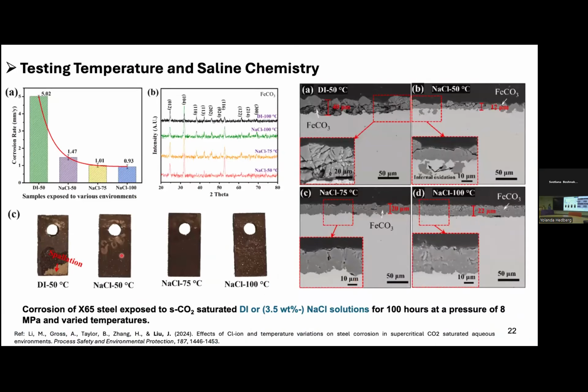So for example, first of all, let's look at this. This 50 means the temperature of the water is 50 degrees C. This is DI water. This is sodium chloride water. If we just look at these two, you can tell the sodium chloride corrosion rate is way smaller than the DI water one. Now, when we look at this one, if it's just sodium chloride solution and we increase the temperature, now we're all talking about statics, that's why I say we may underestimate things. When we increase the temperature, the corrosion rate decreases. So it's the opposite of what we expect.